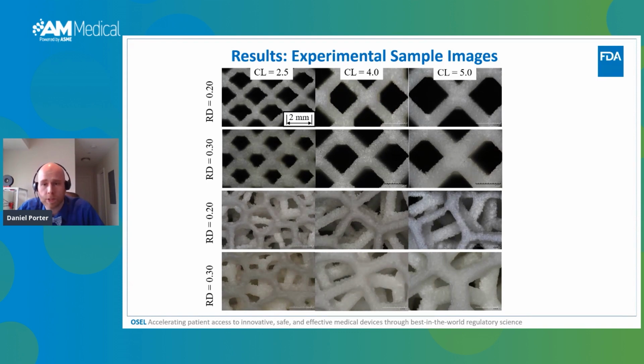It should be noted, though, that the struts on the outside of the Voronoi samples are half struts. This was done to make sure that designs are simpler, also to make sure it's easier to incorporate the samples into the grips. Also to note that this may induce additional performance effects since all the struts are not necessarily the same diameter and may even introduce stress risers.